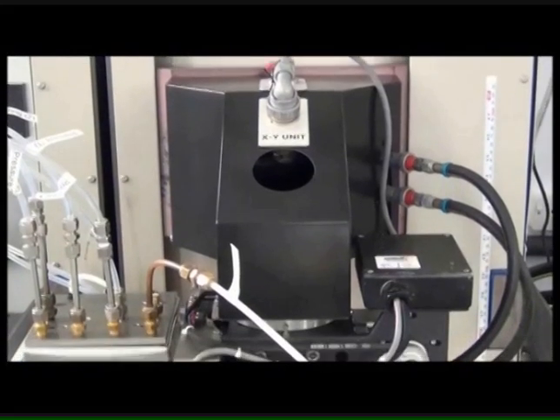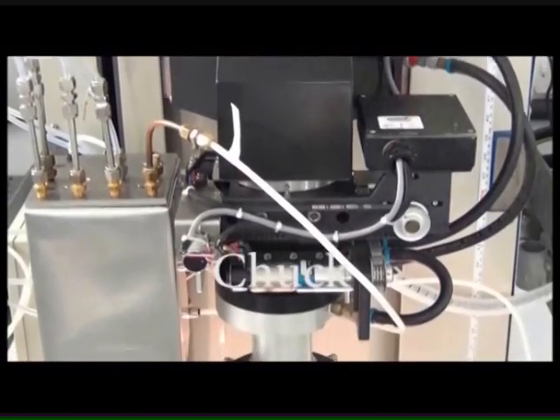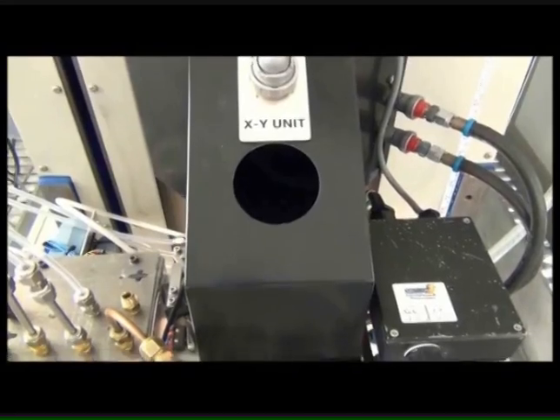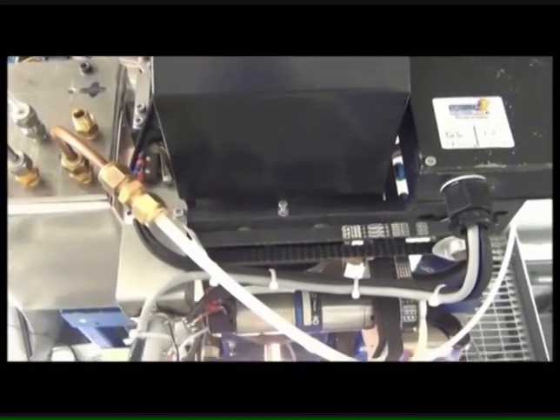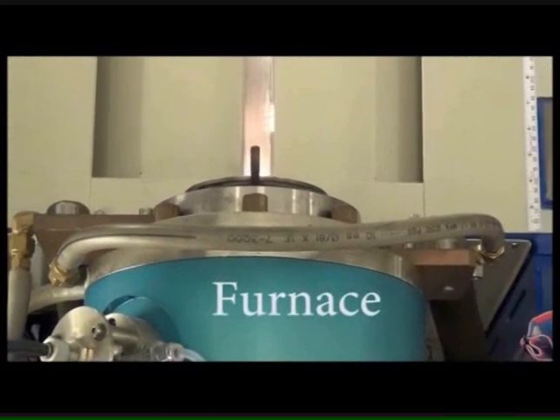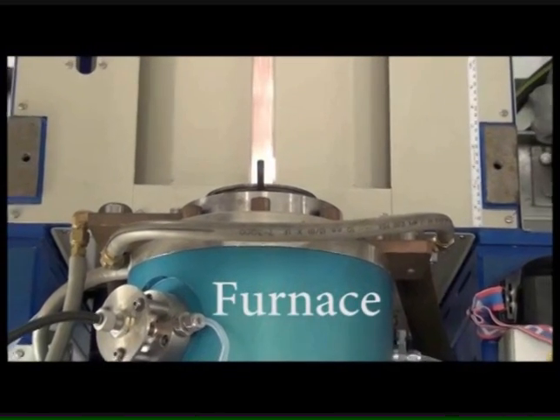The fibre drawing tower is at the centre of our fabrication process. At the top of the tower there is a chuck for holding the fibre preform and various pipes for supplying either pressure or vacuum to the cladding structure. After putting a preform in the chuck it is fed down gradually through the furnace at a rate of a few millimetres per minute.